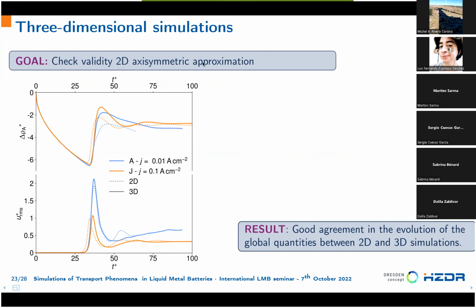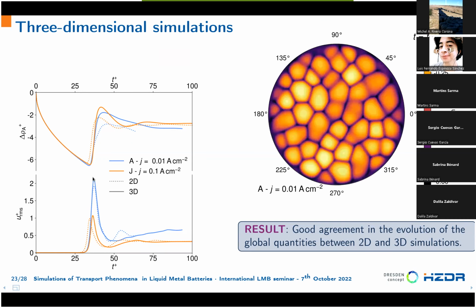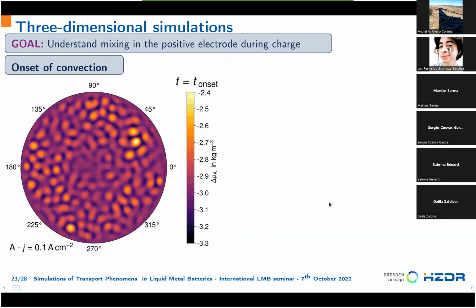First we want to check the validity of our 2D axisymmetric approximation. Here the continuous lines are the 3D simulation and the dotted lines are the 2D simulation. We observe very good agreement between both in the concentration differences and in velocity. But if we look, for example, at the maximum of this curve, we observe that the concentration distribution at the interface is not at all axisymmetric. We can explain this agreement if we look at the evolution.